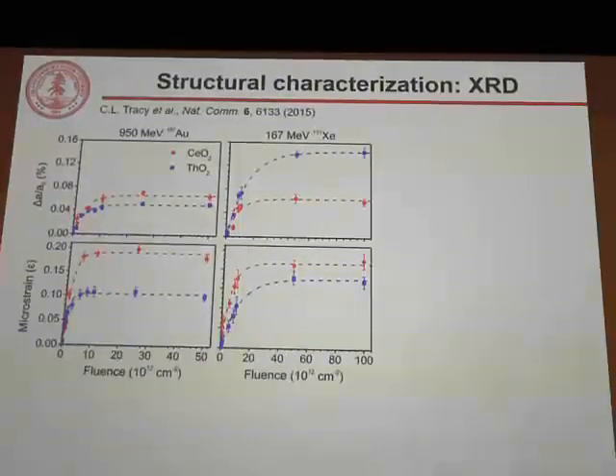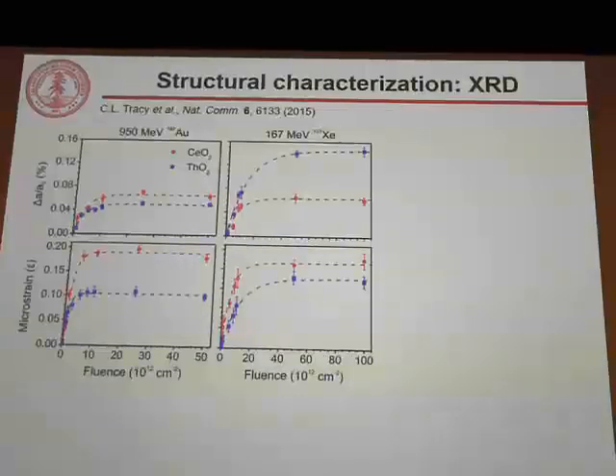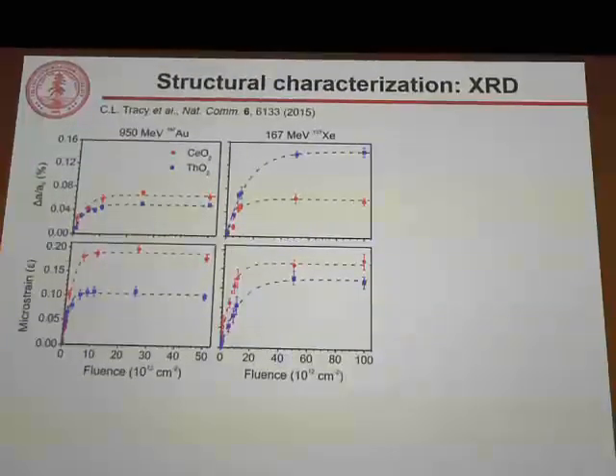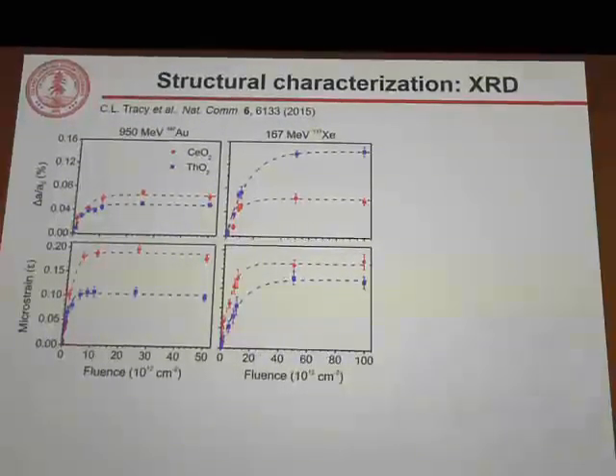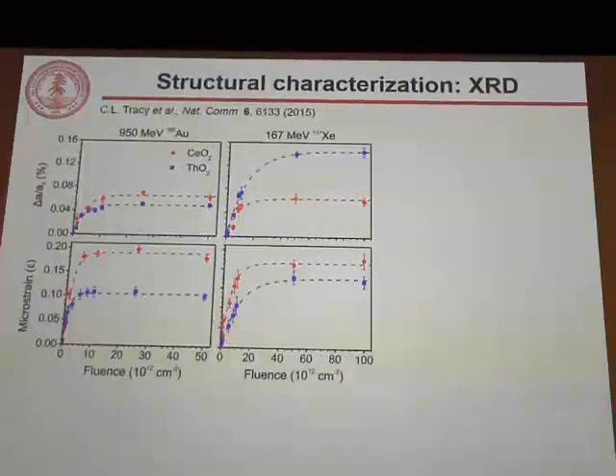On the top, the change in unit cell parameter, on the bottom, the microstrain as a function of ion fluence using Rietveld refinement. So I show here for the two different ions and energies, these changes as a function of ion fluence. And we see some really interesting behavior, particularly when we compare cerium and thorium dioxides. Thorium dioxide in blue shows a dramatic change in the extent of damage, the saturation damage for both properties, when we change the ion energy. Cerium does not. It's almost the same damage regardless of whether we're using 950 MeV gold or 167 MeV xenon.